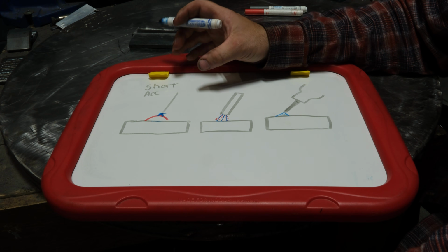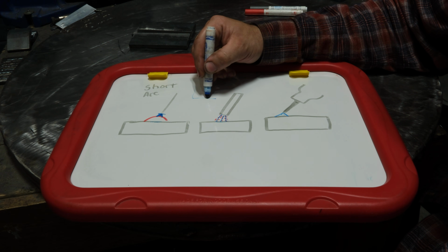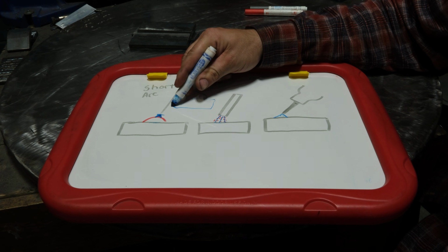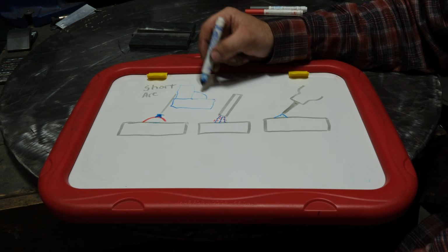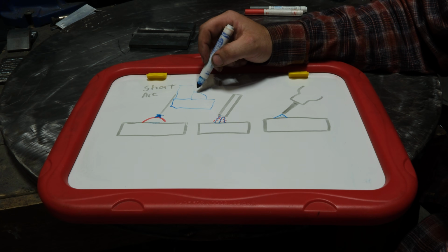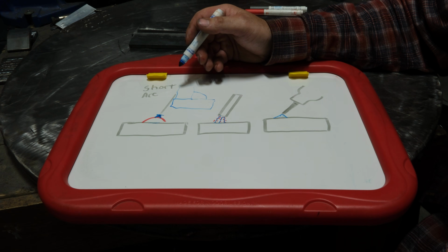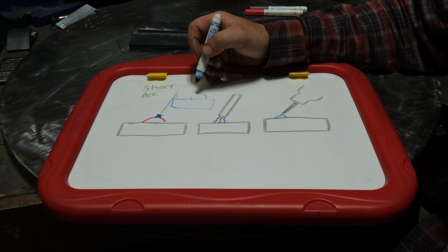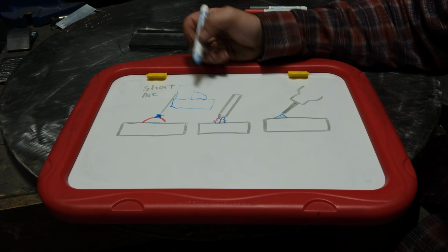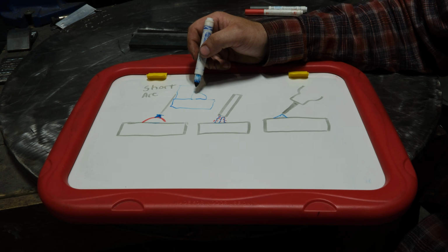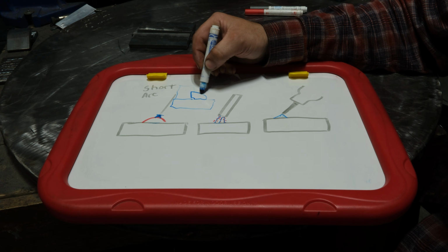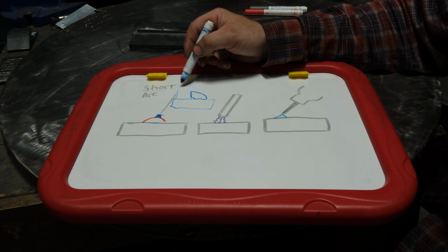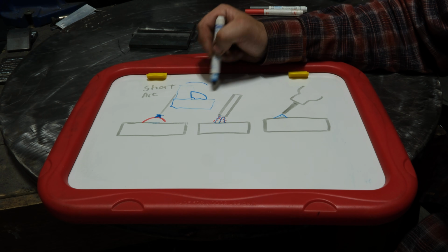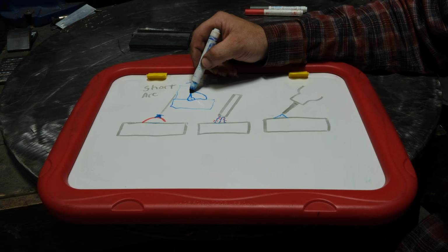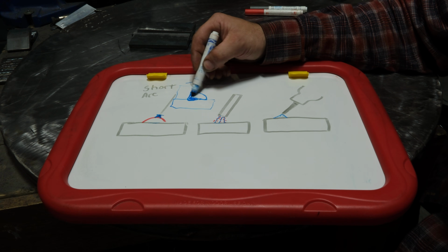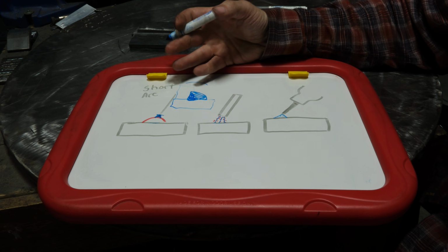Well, again, multiple pass means you're putting a weld that is thick enough for the thickness of material. So say you had 1 inch thick material, that you have a 1 inch thick toe to root weld. Well, yeah, that is putting the appropriate size of weld down for the material you're welding. But if you have very poor sidewall fusion where it's like not bit into the plate, more weld doesn't solve that. Not to mention, again, if your weld looks something like this where it never fused the root, guess what? If this were to ever get bent this way, it's going to tear and the weld will fail very easily, versus if you had a weld that looks something like this where it penetrated and fused all of this in. And that's the point that I'm trying to get across.